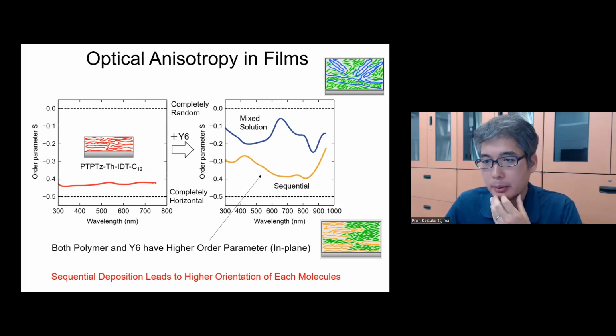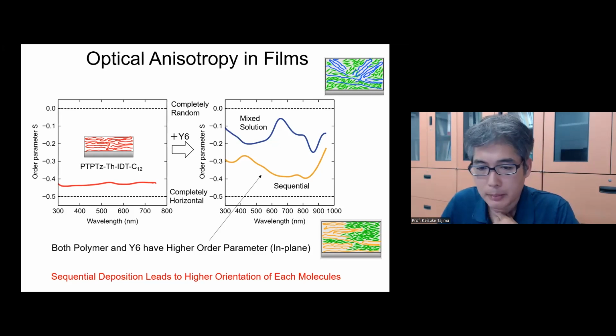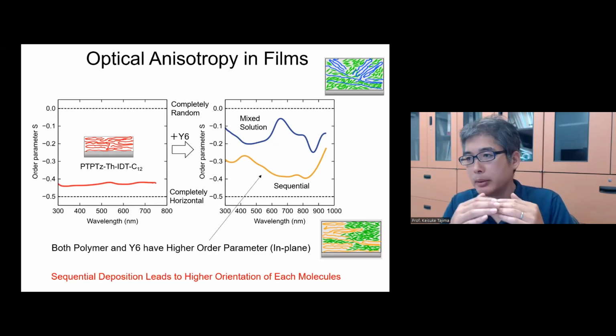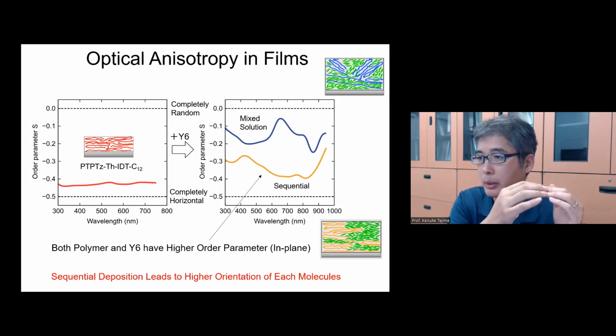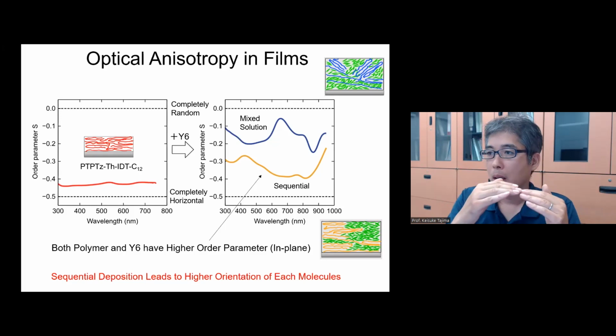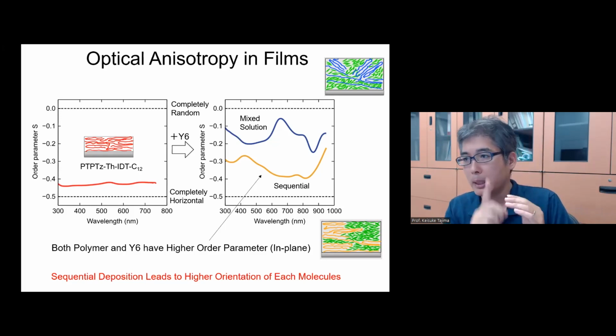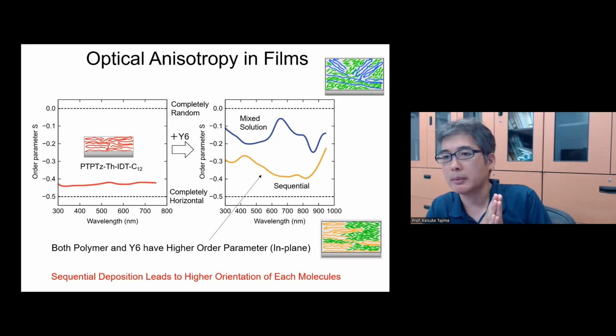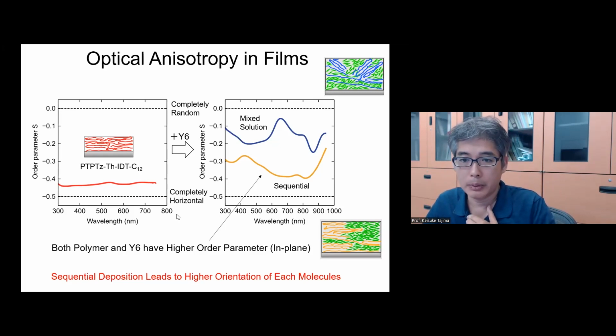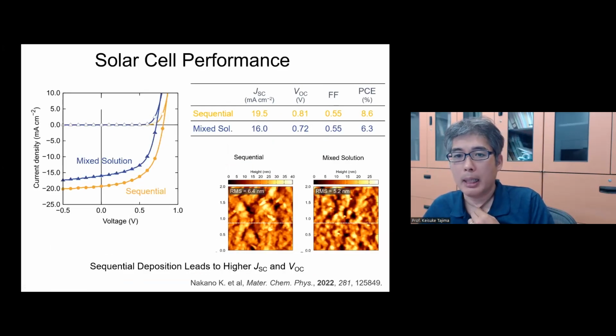Optical property is similar. By adjusting the condition, we can get a similar optical property between these two films. I would say the large difference is after absorption. As I mentioned, exciton diffusion, the diffusion of the excited state of the molecule, can be affected by the molecular orientation, and also the charge transport in the vertical direction is affected by the orientation. We cannot tell which is the main factor for the enhancement of the performance, but I think that both are contributing to this difference. Yeah, mainly higher JSC.